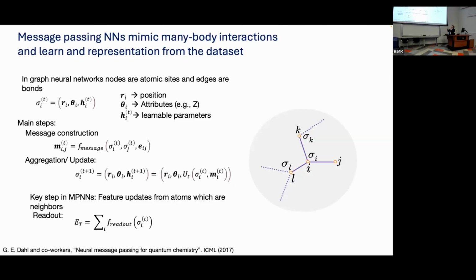So in this way, though we use a graph representation, you can see mathematically this simulates these two-body interactions building up to a many-body interaction. We start from interactions between sites, and then we allow communication between the two, which creates this many-body effect, and eventually we aggregate the final representation in order to make a prediction of the energy. So these representations simulate many-body interactions, and they also have this necessary requirement of being effectively local interactions that are summed up to a global property, which is important for the energy. So these message passing neural networks have become state of the art.